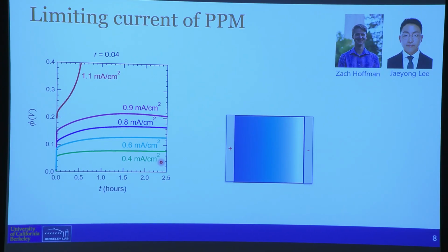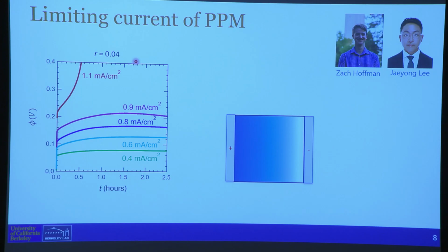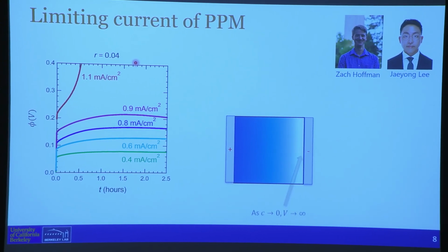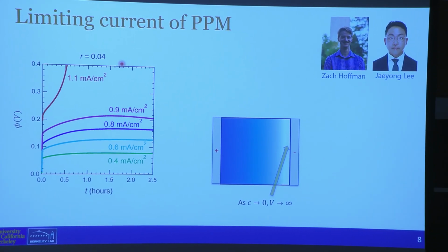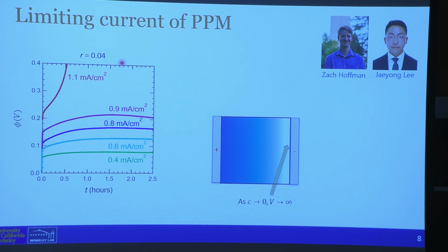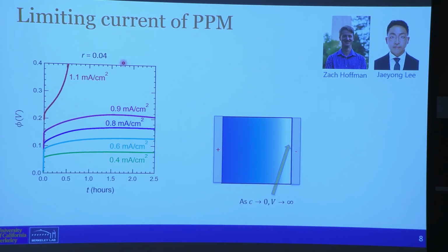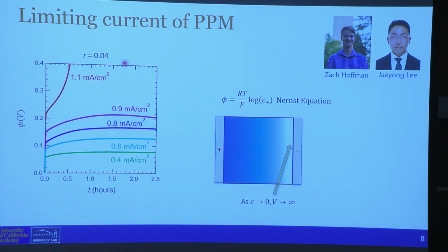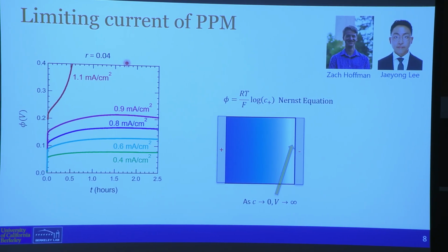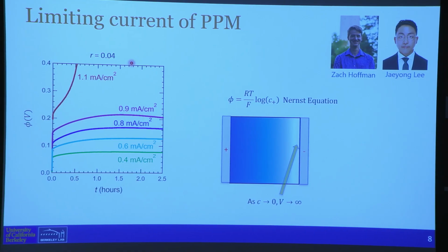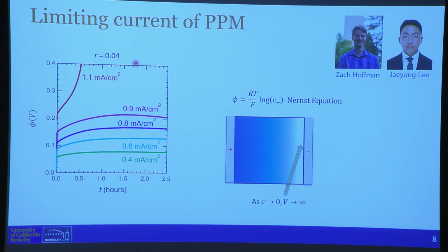Yeah, so you're increasing the current density, and between 0.9 and 1.1 in this case, at an R of 0.04, you see a divergence in the voltage. And that divergence is easily understood. What happens is that the concentration next to the negative electrode is approaching 0. And we are used to using the Nernst equation, which is some constants that give you a voltage in front, and a concentration of positive ions. As that goes to 0, it goes to minus infinity. And so that's where the voltage is diverging. Okay.